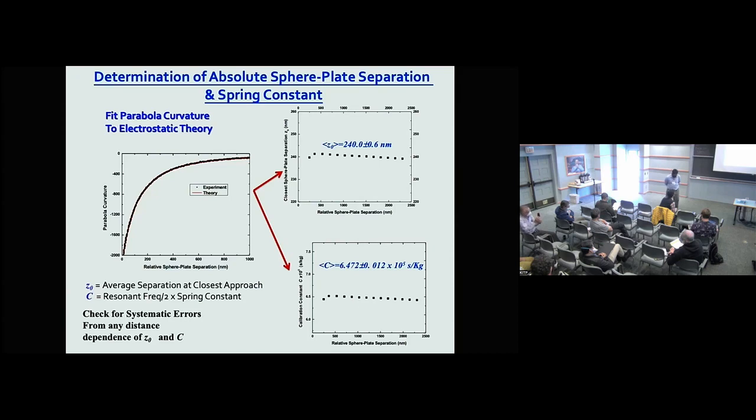Because if you look at scattering, your damping term, you use a gamma, and even if you take gamma from the measurement, when you deposit the metal on the sphere, the gamma depends on grain size and thickness, right? And furthermore, gamma depends on frequency.